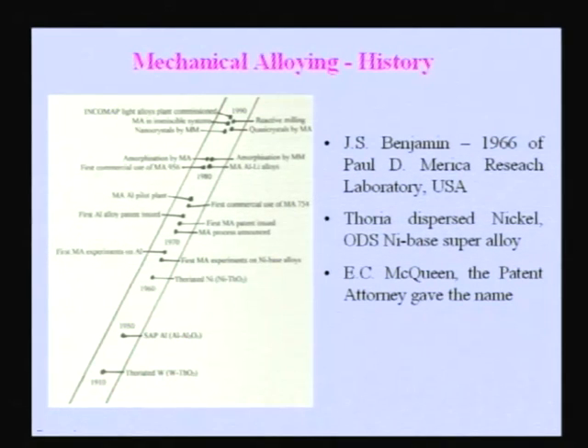So this is the difference between these two, and people have shown that even pre-alloyed powders, intermetallic compounds, can be made into an amorphous. And nanocrystals by mechanical alloying came around 1987. Quasicrystals by mechanical alloying also almost 1988. Reactive milling started around 88-89. Then mechanical alloying in immiscible systems, that means systems where A and B do not dissolve into each other under normal conditions. For example, there are a number of monotectic systems. We know in the phase diagram there is a miscibility gap in the liquid itself. That means A and B do not dissolve even in the liquid state. Even such alloys can be made into an alloy by mechanical alloying. We will talk more about it later.